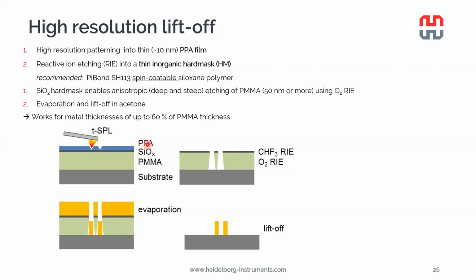We want to make it as thin as possible so that we can also pattern using the maximum resolution enabled by the sharp tips. After the patterning, we first etch the patterns from the PPA into the silicon dioxide in a reactive ion etching step. Afterwards, we transfer the pattern further into the PMMA below using oxygen plasma in a reactive ion etcher. The silicon dioxide is, as I mentioned, a very high quality oxide, so it can withstand etching of even hundreds of nanometers of PMMA if required.